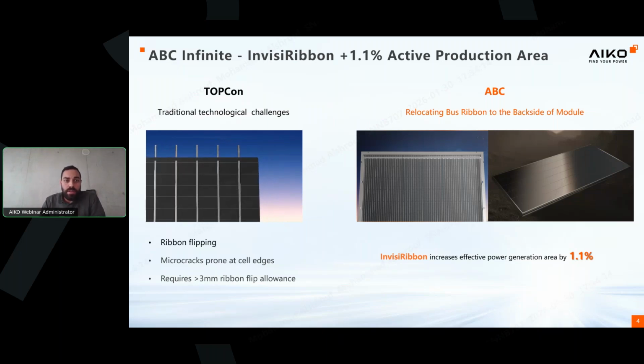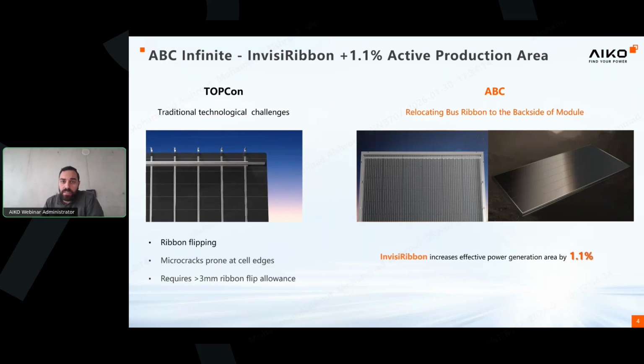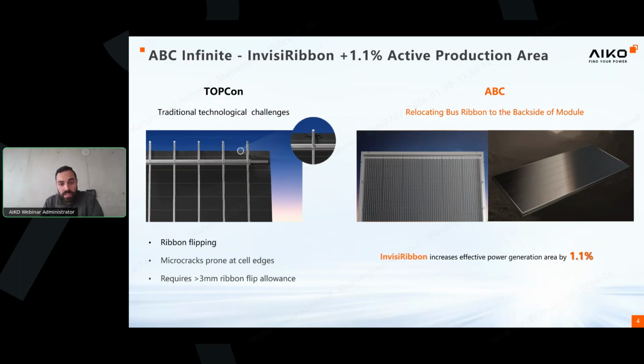So talking about the infinite technology, you know that this helped us to increase the active production area by 1.1%. This is also from the smaller panel before. And this is an advantage actually to the back contact panels, because we are able to basically flip the ribbon to the backside, which is kind of a challenge for the TOPCon panels, because they have a front circuit, and flipping the ribbon to the backside will have a high potential to cause micro cracks at the edge of the cells. But in our case, for the back contact technology, the circuit is already built from the backside, and it's way easier to have the ribbon on the backside, and we call it invisi ribbon. So this is one improvement to increase the power with 1.1%.